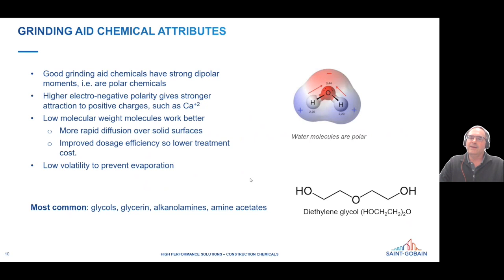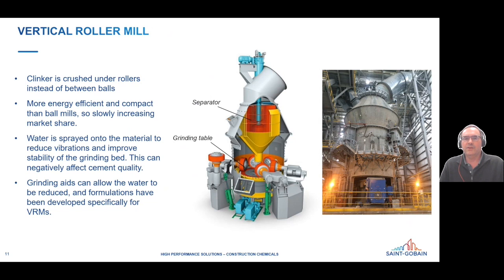So one last topic on grinding aids I just want to mention. There's another type of mill called a vertical roller mill, which operates on slightly different principles. In this case, the clinker is ground by having this rotating table, and the clinker is carried under these heavy rollers, which just crushes them. In a vertical roller mill, the grinding aid can help to stabilize the vibrations of the VRM grinding table.